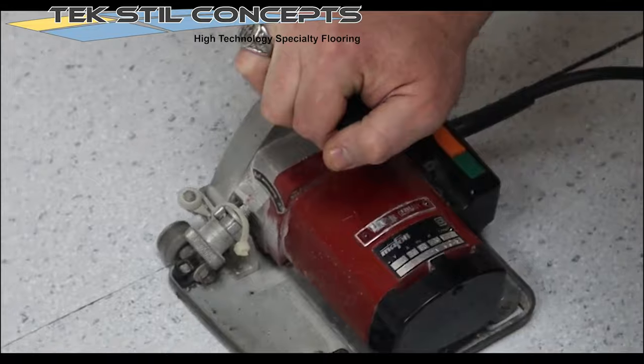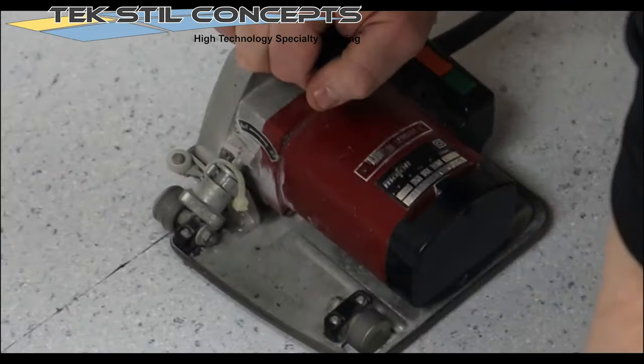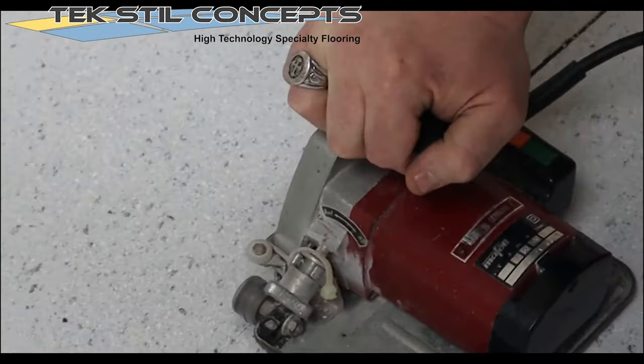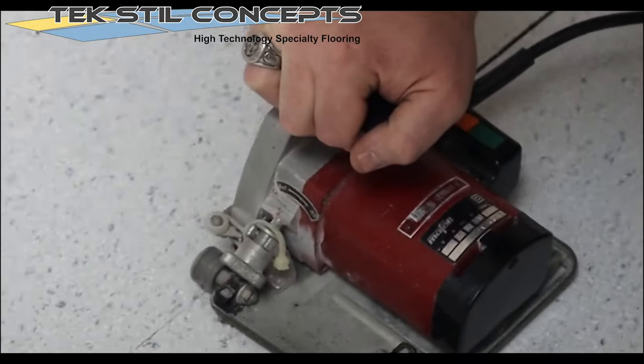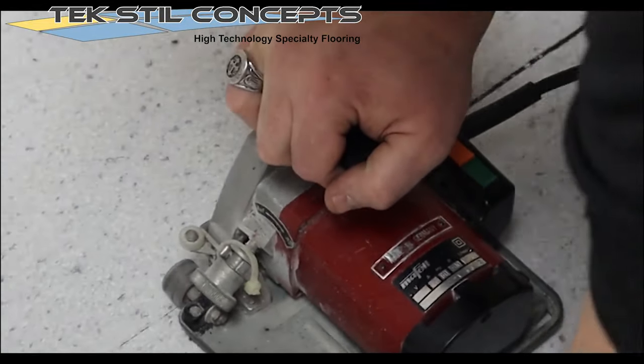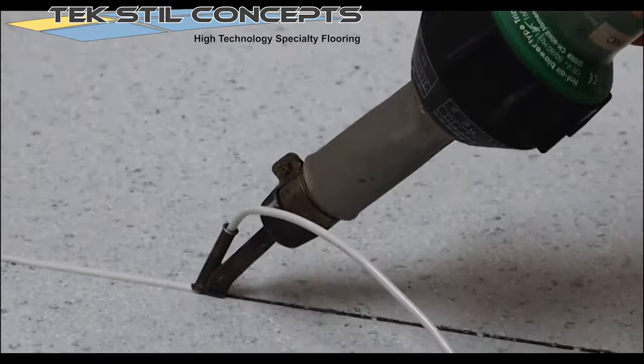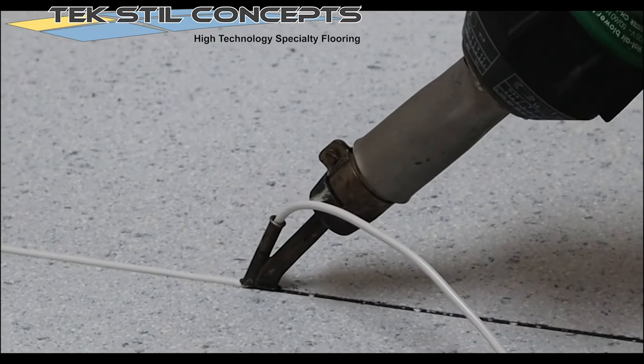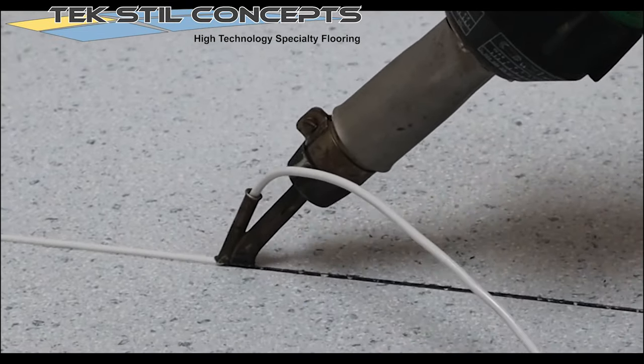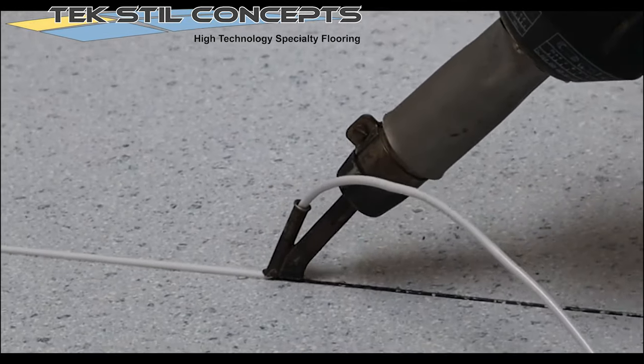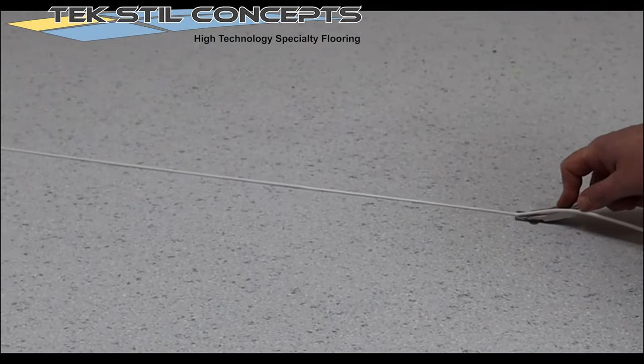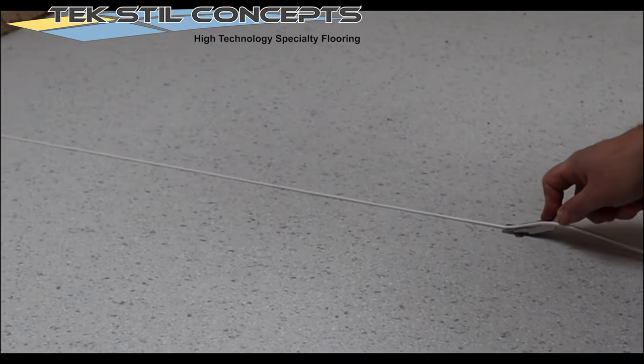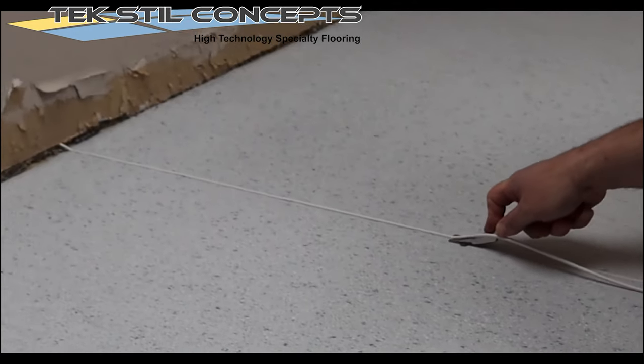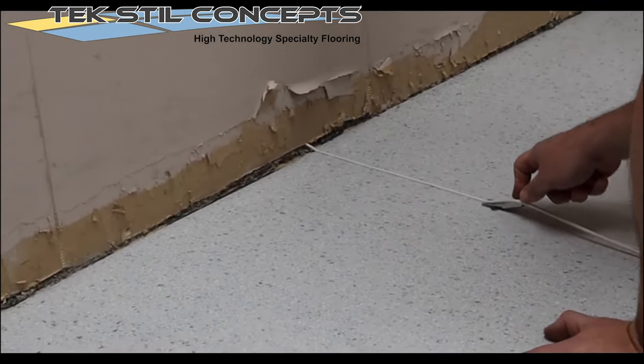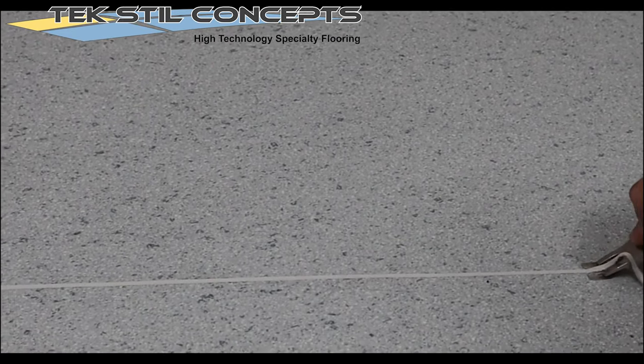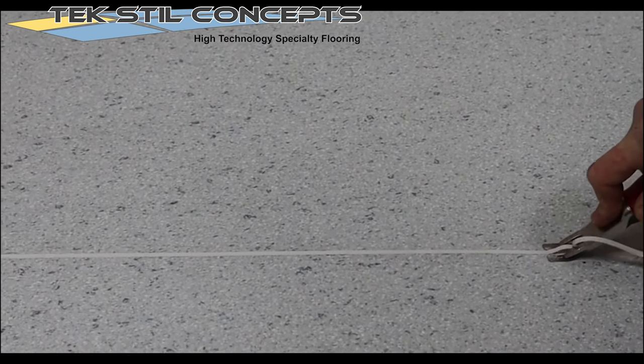After waiting for at least 24 hours, the seams will be ready to be grooved and heat welded. Use excess sheet vinyl to adjust settings for the groover and the heat welder prior to working on the installed area. After the welding rod has cooled, the welding rod can then be trimmed flush to the floor. Always trim in two passes. Trimmed welds should be glazed.